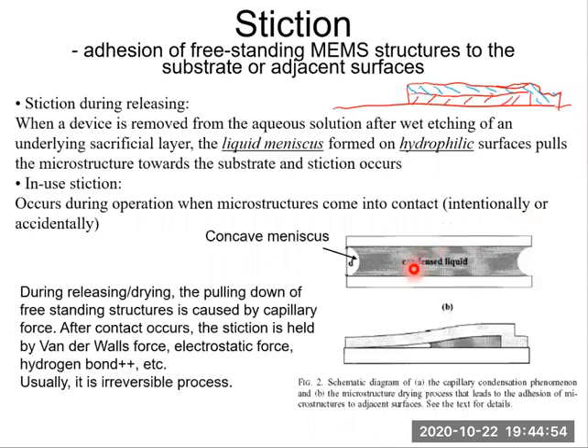Then the meniscus formed between the cantilever and the substrate is concave. Right? We have this concave meniscus because the silicon surface, due to the native oxide, is hydrophilic. We have discussed the hydrophilic surface before, right? The contact angle is less than 90 degrees, right? That's hydrophilic. So we will have this concave meniscus. Then the pressure inside this condensed liquid is less than the pressure of atmosphere. So the meniscus force, the pressure inside is smaller.